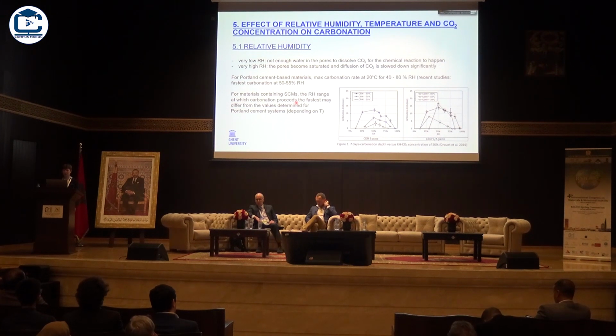What about relative humidity? Actually, the optimum relative humidity for carbonation is in a wide range between 40 and 80%, more specifically, mostly between 50 and 55%. But this may also depend on the type of supplementary cementitious materials, because here, for instance, at the right-hand side, for a slag paste, you can see that depending on the temperature, the maximum carbonation rate may be at a different relative humidity value.